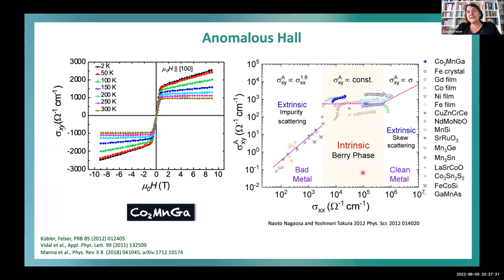To really prove that the anomalous Hall effect is related to the intrinsic Berry phase, you have to investigate rho xy versus rho xx. So you have to measure resistance in different directions, and then you see the relation, and if the rho xy is constant, then we probably have intrinsic Berry phase. Also the value of rho xx tells us a bit in which area we are. And this here is cobalt 2 manganese gallium. So it's lying where it should lie for the intrinsic effect.